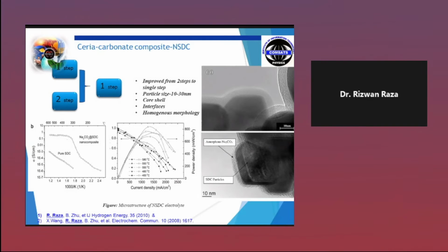First the host material was ceria, doped ceria, meaning gadolinium doped ceria and samarium doped ceria, then coated with different carbonates. And you can see from this electron image, the TEM image, here is the carbonate, and inside is the doped ceria. So there is an interface. Actually, this interface can enhance the ionic conductivity of the material. Ions can pass through this way. We also gave it the name of a highway for the ionic conductors, to transport the ions through this path.